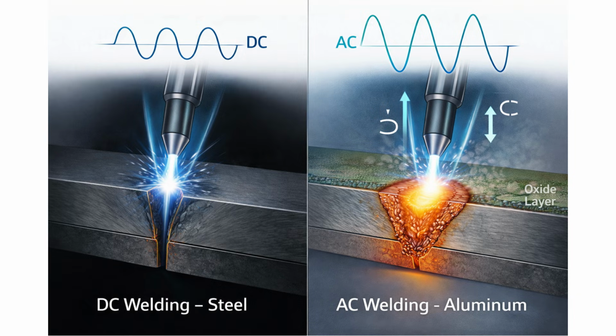One unique aspect of TIG is that we can use either AC or DC current, and the choice matters. DC electrode negative, or DCEN, is used for welding steel, stainless steel, and most other metals. The electrons flow from the electrode to the workpiece, creating deep penetration and a stable arc. AC current is primarily used for aluminum and magnesium. Why? These metals form an oxide layer that melts at a much higher temperature than the base metal. AC provides a cleaning action that breaks up this oxide layer during the electrode positive portion of the cycle, while still providing good penetration during the electrode negative portion.